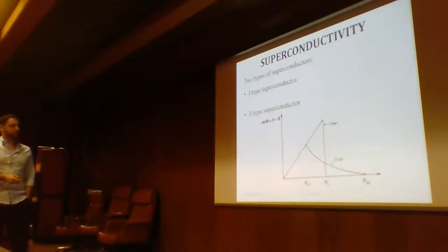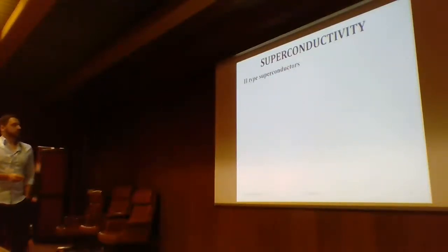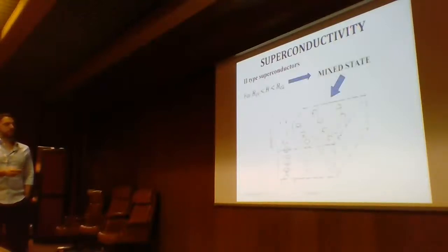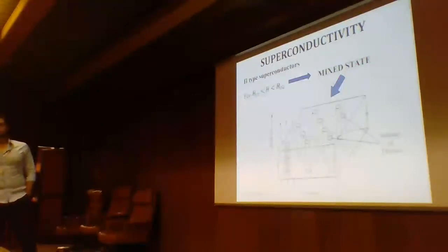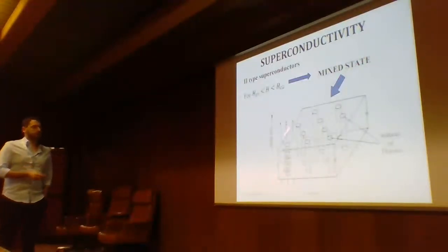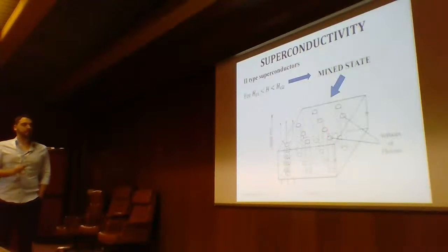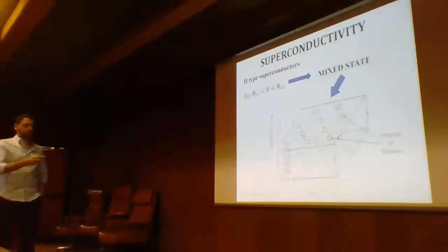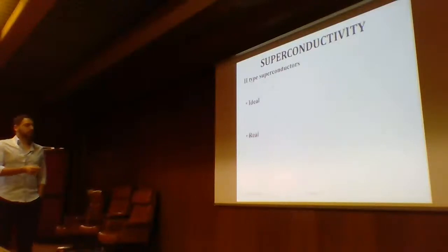But what happens if we put the field between these two particular fields? If we put our field between the lower and upper critical field, we are in the so-called mixed state. That is a very important state in superconductors, because it is characterized by the entrance of the magnetic field in the material in the form of quantized flux. So you still have superconductivity, but with magnetic field that has penetrated your material. And this is a very important characteristic.